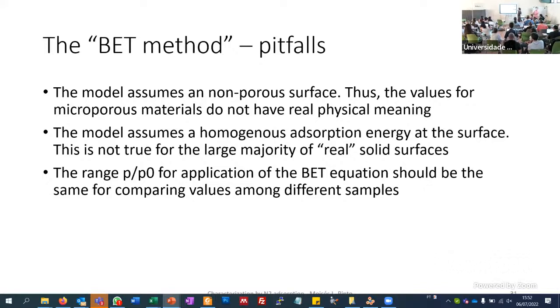The model also assumes a homogeneous adsorption energy at the surface, and this is not true for the majority of real materials. You have parts of the material, for instance in this case, which are benzene rings, other parts which are zirconium oxide clusters. It's very difficult to conceive that the nitrogen molecule will interact with the same energy everywhere. So please take this into consideration when applying this. Nevertheless, this is a useful model to compare your materials with others, of course. But you need to remember some of these pitfalls.